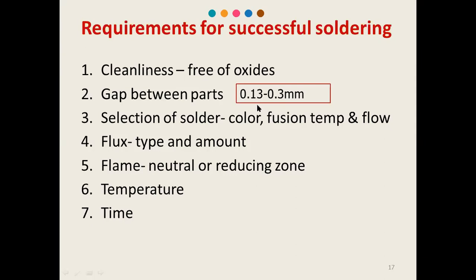If the gap is very narrow, the strength will be hampered because of the development of porosity. Because if the space is too narrow, there is incomplete flow of the filler metal, or there is flux inclusion. If the gap is too wide, what will happen? It will again hamper the strength, because the joint strength will be the strength of the solder metal, and the solder metal is a little bit low in strength as compared to the parent metal. The second drawback is that there is a tendency for the parts to draw together as the solder solidifies. So in both conditions, there is a reduction in strength if the gap is less or more.